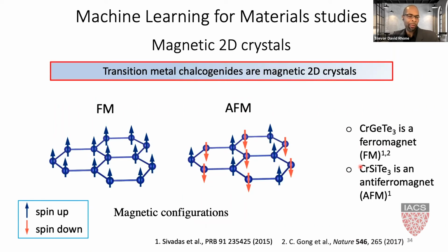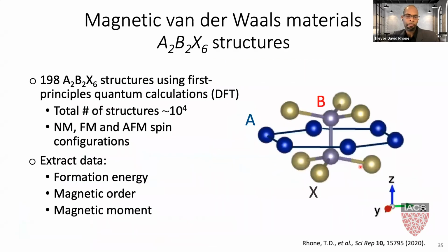How much can we explore this structure-property relationship? So what I decided to do was make different chemical substitutions at A, B, and X sites and see what their resulting magnetic properties were. So I took this A2B2X6 crystal structure, and I decorated the A, B, and X sites using different atoms from the transition metals for the A sites, group 4 and 6 for B sites, and group 6 for the X sites.